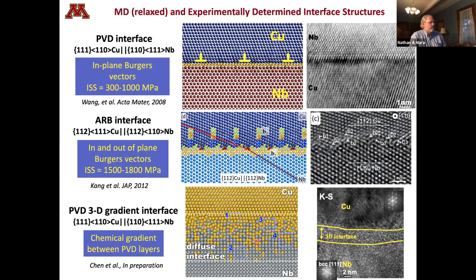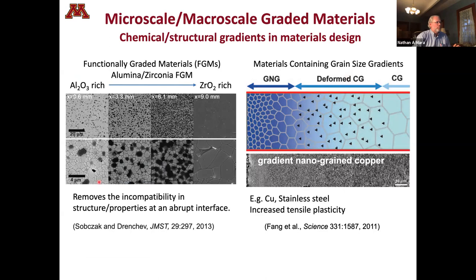So the idea of grading an interface is not new, right? This has been around for a long time. You see it in what are known as functionally graded materials. Here's an example between alumina and zirconia. Over the span of millimeters, you can take an alumina-rich material, add a little more zirconia, and a little more zirconia until it becomes zirconia-rich. These types of microstructures are used to relieve incompatibilities in either mechanical properties or the structure in an abrupt interface.